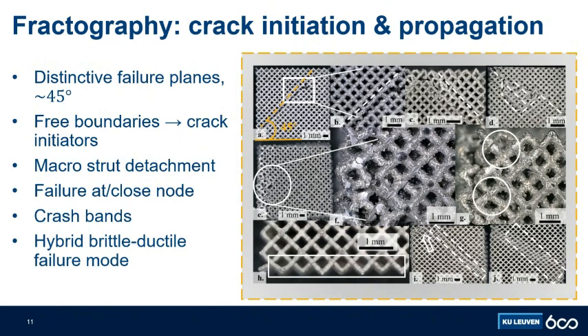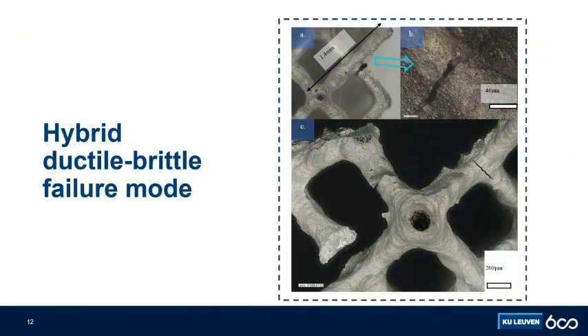This is more observable over here. On top, we can see a more ductile failure with a darker surface, more plasticity occurring, dimple after dimple. While on the bottom, we can see a clearer fracture surface, resembling the cleavage from the theory of materials, thus strongly indicating a more brittle failure mode.